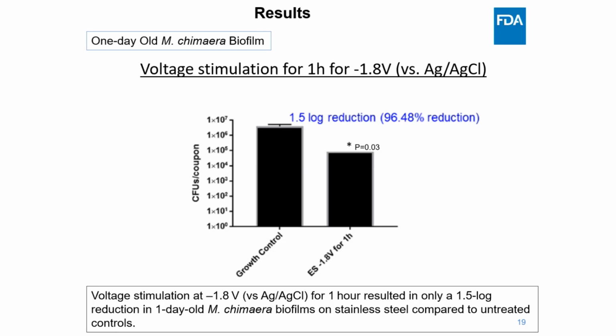We applied this voltage for 1 hour to 1 day old Mycobacterium chimaera biofilm on stainless steel coupons. It's important to note that mycobacterium biofilms typically require up to 40 days to form mature colonies, so this model reflects a very early stage of a biofilm for M. chimaera. After stimulation, we observed about a 1.5 log reduction in viable biofilm-associated bacteria. This is equivalent to approximately 96% reduction of the viability compared to the untreated control. While this is a measurable effect, it falls short of the 3 log reduction threshold generally considered by the FDA for intermediate level disinfection for mycobacteria.